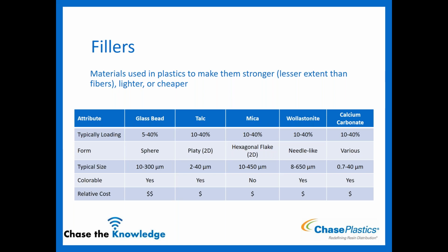So glass bead essentially is taking this long cylindrical fiber and then just having them in little sphere-shaped beads instead, so you still get a little bit of the boost in performance without having to deal as much with the issue of the shrinkage. So fillers, as I mentioned, because they don't have that aspect ratio, they're more uniform and sphere or 2D in shape, you're not going to have that issue with the shrinkage.